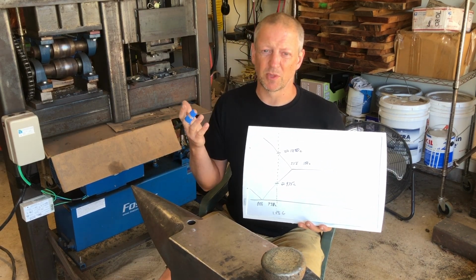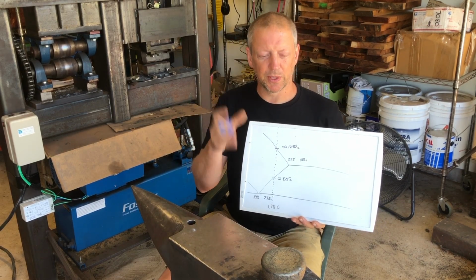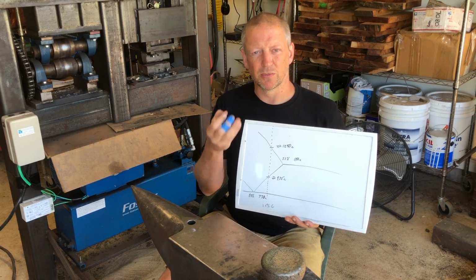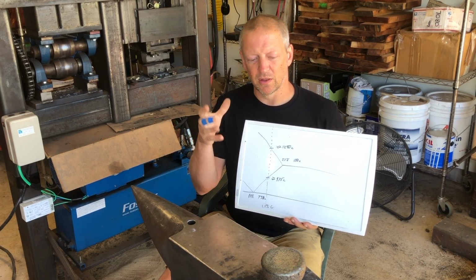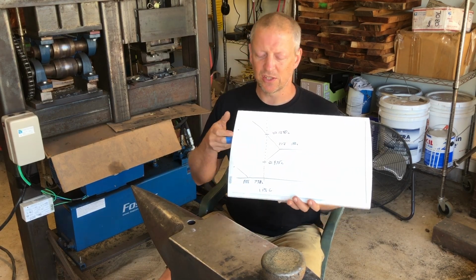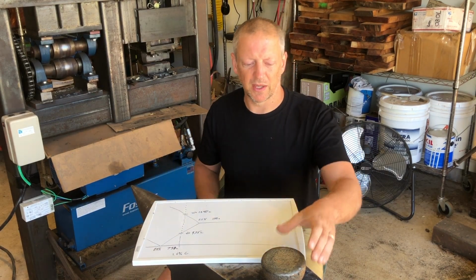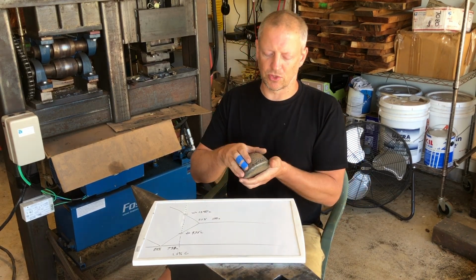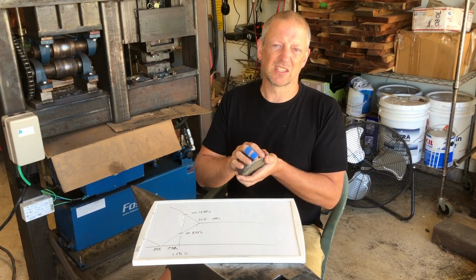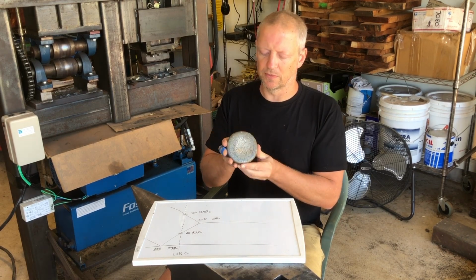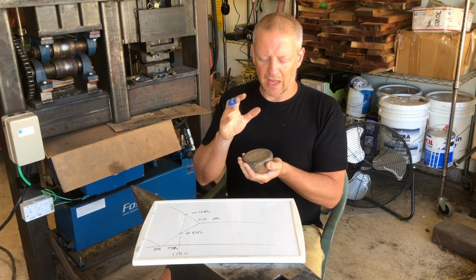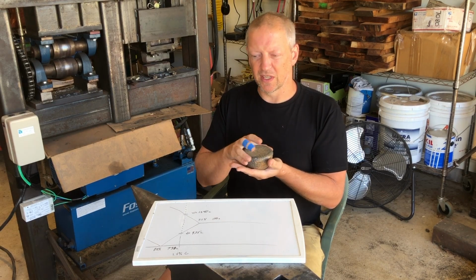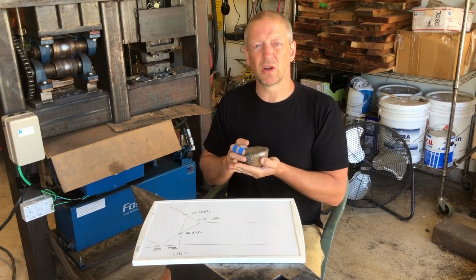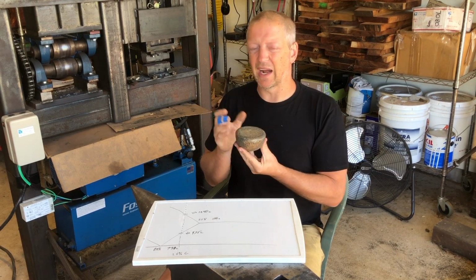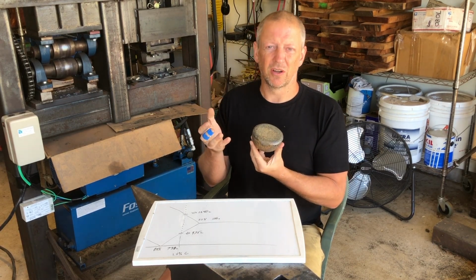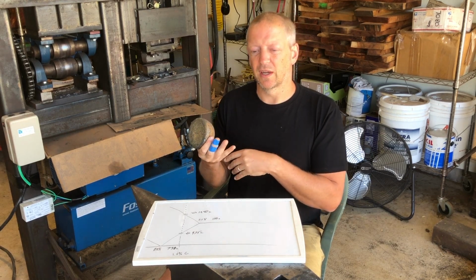And they were doing this roast for 12 hours, sometimes more. And they were putting the ingots back in a crucible that was lined with iron oxide, because in addition to the heat aspect and changing the internal structure, they were also trying to create a case of decarburized material. Part of the reason for this was that looking at historical ingots, many of those ingots had high sulfur contents. Higher sulfur contents lead to hot shortness,